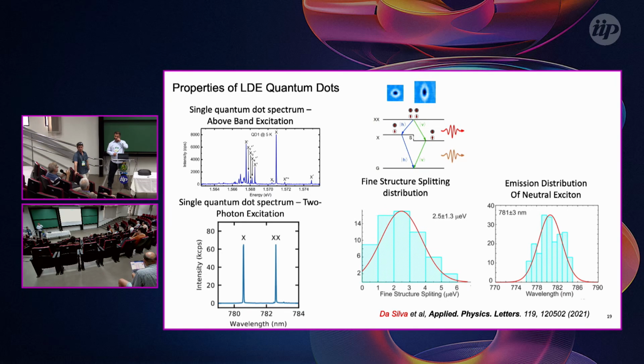This is what I don't understand. What is the difference between if you excite with 1 photon and 2 photons? Because the carrier will be created in the valence band of the aluminum gallium arsenide. That's correct? And then drops to the quantum dot. Yeah, but for the two photon excitation, basically what you do, you use this tunable laser, and you come more or less here in the energy that you just excite two electrons to the conduction band. You give an energy enough for exciting just 2 electrons to the conduction band. Understand?